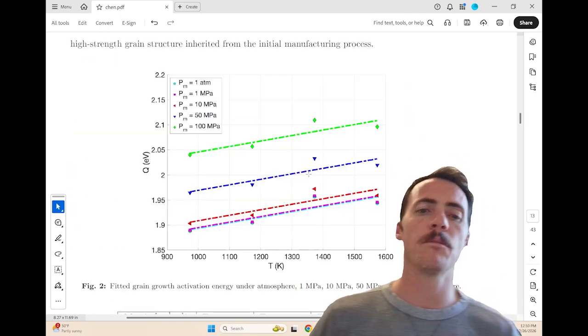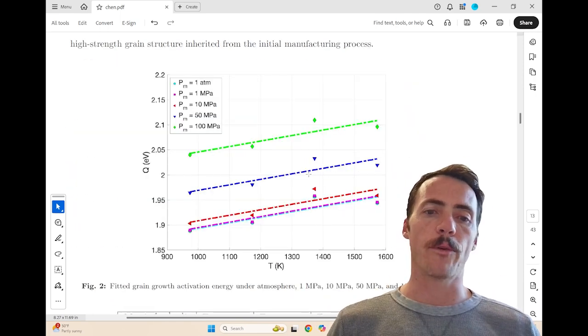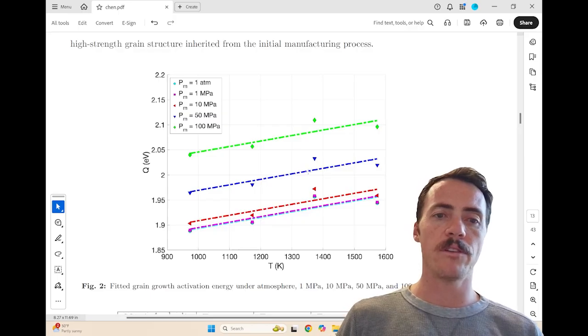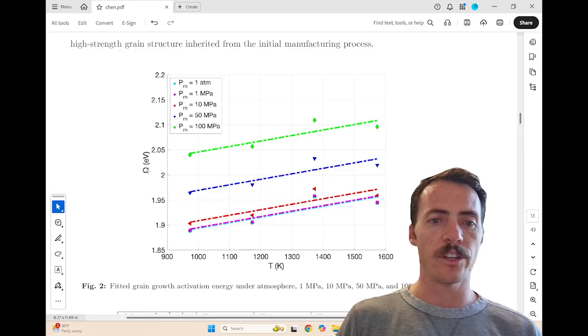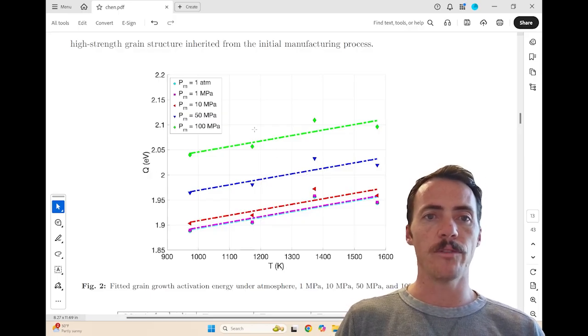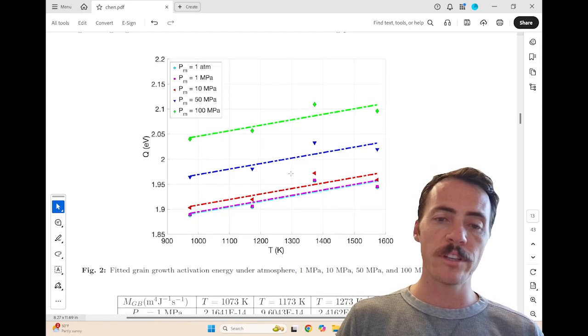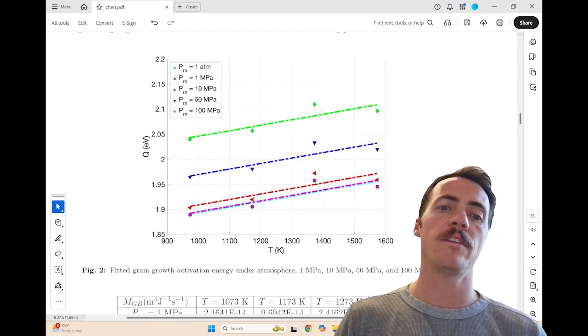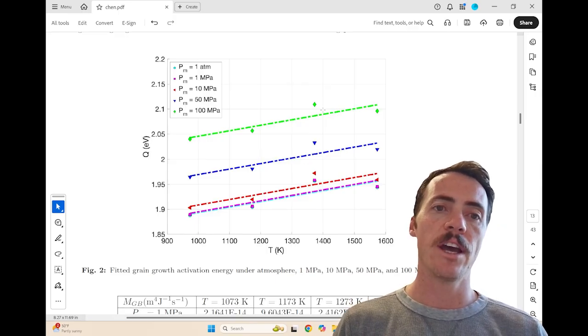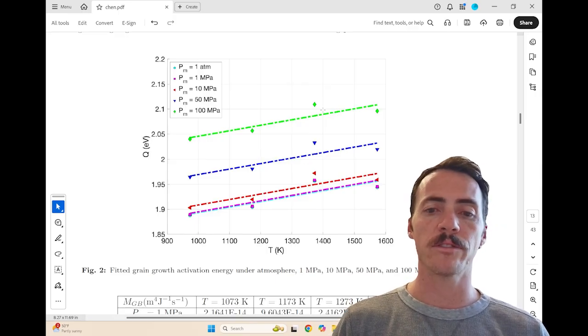Here's an example of some of the activation energies for grain mobility when they measure them. You can see now this is showing you the activation energy Q as a function of temperature, and you've got 5 different pressures here. And obviously, pretty significant increase in the activation energy as you go towards higher pressures, right? And that's a big deal.